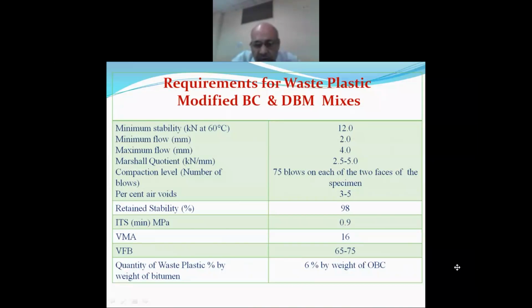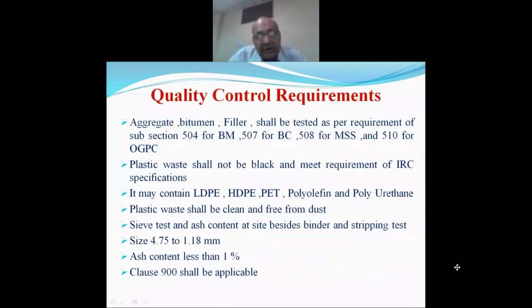Now the bituminous concrete we generally use on national highways, state highways, and sometimes on MDR also. Plastic waste modified bituminous concrete is a continuously graded design mix prepared in hot mix plant, may be used on national highway with higher traffic. Mix shall be prepared in modified hot mix plant and transported in covered tippers. 30 to 50 mm thickness of plastic waste modified BC mix is recommended. A viscosity grade bitumen, preferably VG10 or VG30, VG10 for cold climate areas and VG30 for hot climate areas, shall be used for plastic waste modified bitumen.